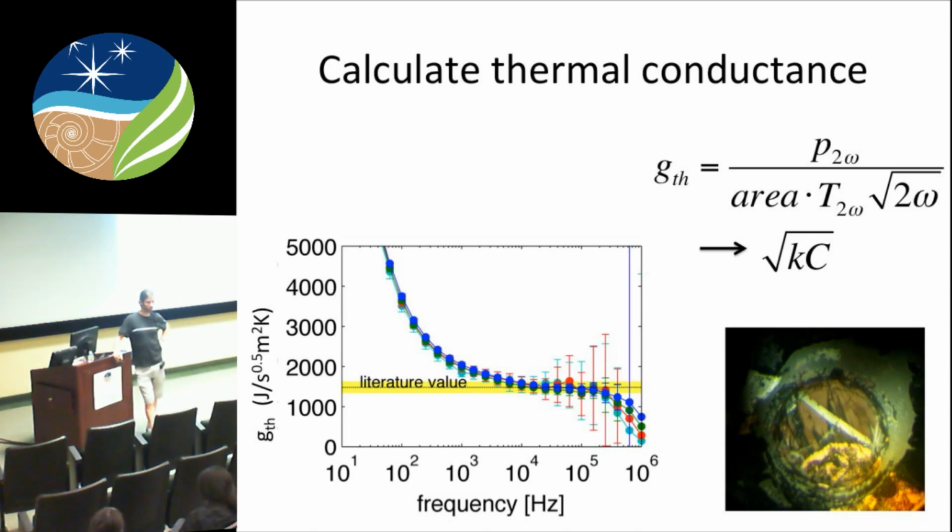I guess my concern is that this line can also be temperature dependent. It is, because at low frequencies it reflects more the thermal link to the outside world, and at high frequencies it reflects more the heat capacity of whatever is next to the heater. I've looked at it, and it is temperature dependent. There's not an easy way to say what every kink means.